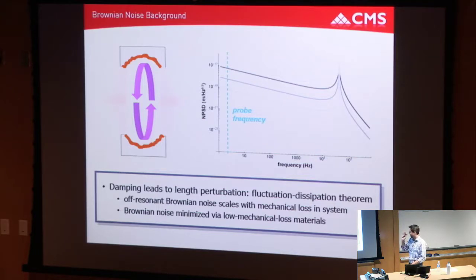And if I push to some totally unphysical process where the system has no mechanical loss, there'd be a delta function here at resonance. I'm showing one isolated mechanical resonance, and you'd have your forest of mechanical modes. They would basically have infinite noise, that delta function on resonance, but they would have no noise off resonance. That's an extreme case, but what you're trying to do is shape the noise spectrum to pack all the motion in and around the mechanical resonances and have these quiet regions in between, and bring down the off-resonant tails at DC. So there you can see how, if you increase the mechanical quality factor of the system, you can reduce this off-resonant noise, this off-resonant motion.